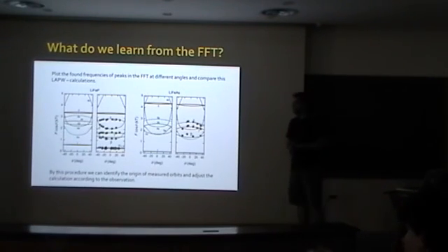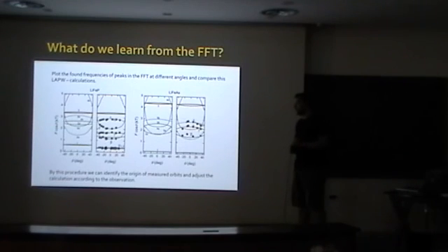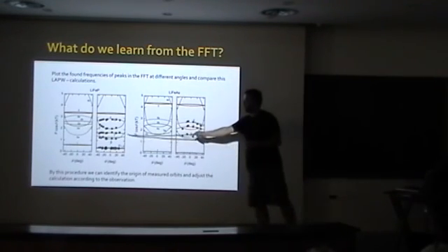Short question. In heavy fermion systems, I think it's much easier. When people want to know if they have seen all the bands, they compare the specific heat, for example, the Sommerfeld coefficient, with what they measure with dHvA. Can you do that? Yes, you can do that, but there is only data on lithium iron arsenide so far, and only one publication where they mention the number. They do not show any data for the Sommerfeld coefficient that we would need for that, and that seems to agree with what we have so far in the band structure calculation. But certainly more has to be done on that, especially on lithium iron phosphide, where there's no specific heat data yet that I know of, because the samples are just too small to measure it so far. This is certainly something that we try to compare, and from the band structure and what they stated, we come pretty close to that value.